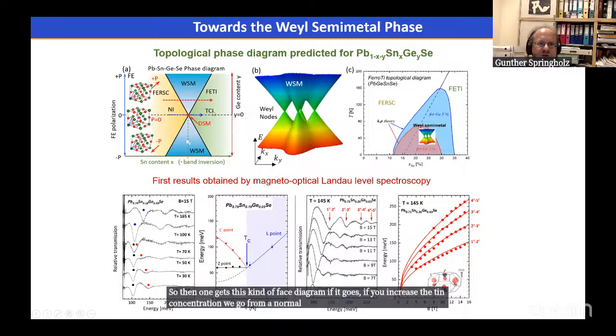So then one gets this kind of phase diagram. If we increase the tin concentration, we go from a normal insulator to a topological band inverted insulator. Without ferroelectric polarization, we would go simply to a band closing at this point here.